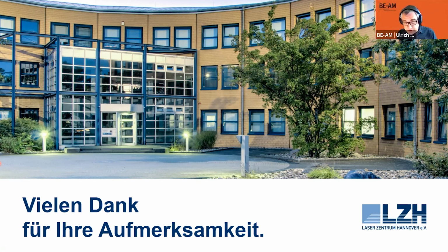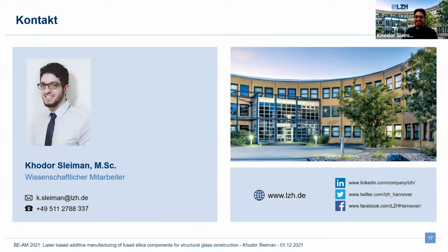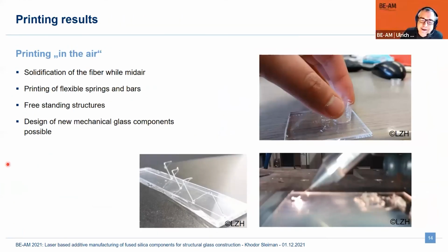And yeah, the small components you showed, which were shown at the trade show on the Formnext stand, were actually the smallest ones which we had. It's a size of what, 2 by 2, but importantly the glass surface quality was very good. Any fracture in the surface of glass would directly mean that it's getting complicated. And I was impressed. I haven't seen that one. A glass spring, well, that's super cool. For sure, we can identify new fields with that one. Or printing glass into the air. Another nice aspect.